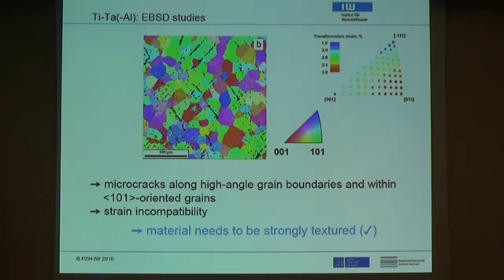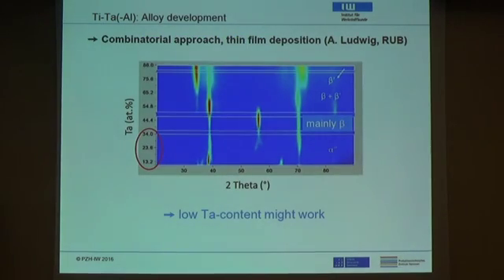Some of the grains do transform, others do not, and then you get locally high stresses, and that's what's causing the cracks. I think there's a pretty obvious solution to this problem. One basically needs to strongly texture the material so that all the grains have more or less the same orientation, and then the problem is solved. In the next step, we did some combinatorial research. Actually, this was done by a colleague of mine, Professor Ludwig, at the University of Bochum.